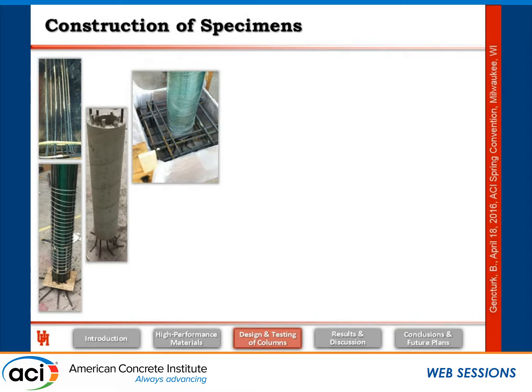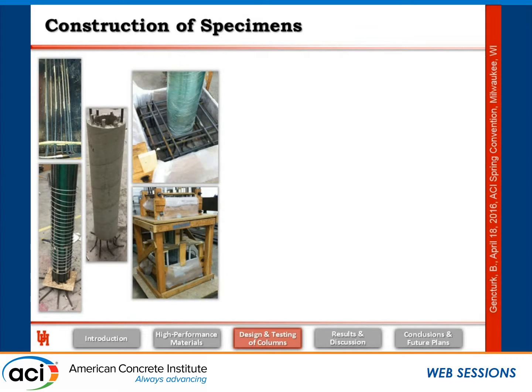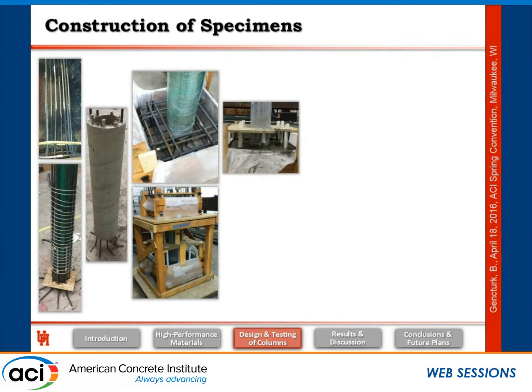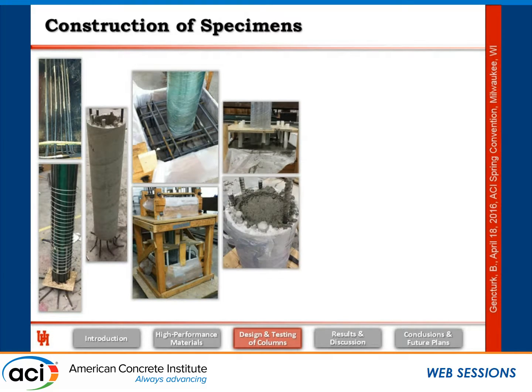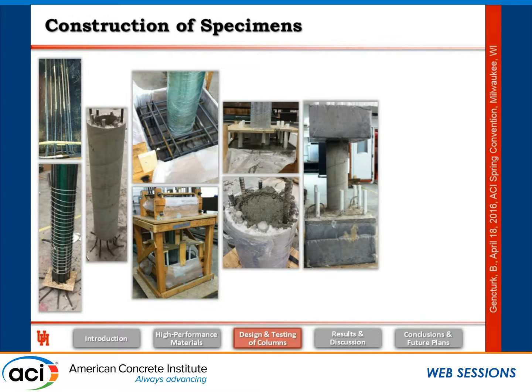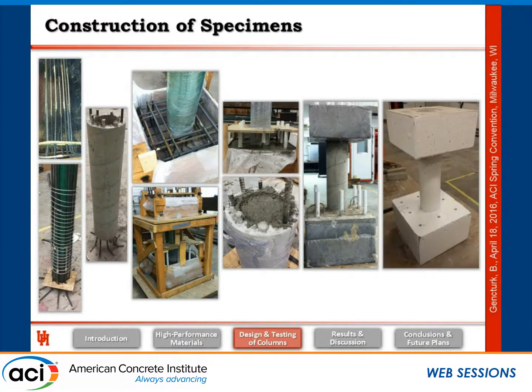ECC is almost self-consolidating. It doesn't require really any vibration, so you just pour it inside the gap, and then you get this tube here. And then we put this tube inside the foundation. We assembled the formwork on top of it, and then we poured concrete in the foundation. We filled the tube. And then this is after we removed the formwork, and then we cleaned it up. We cut these PVC tubes and so on. And then this is what we get eventually.